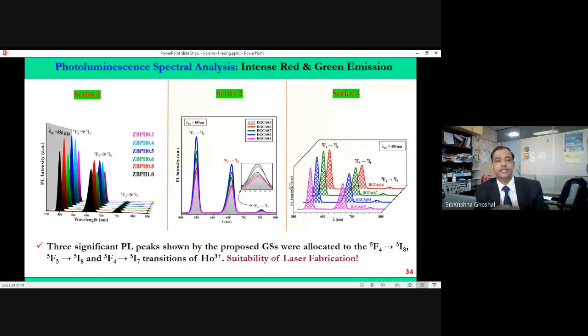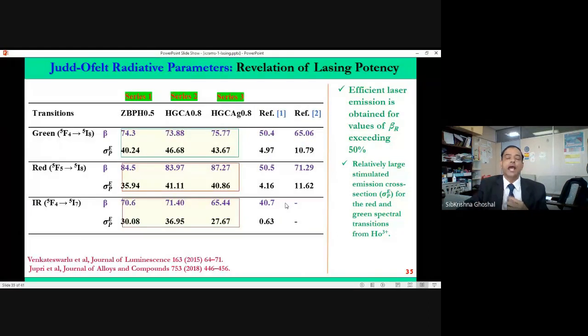Then we look for the photoluminescence, which is the emission spectroscopy. And we see intense red and green emissions. So these materials are really suitable for red and green laser fabrication. And for the first time, you can see the literature and check, for the first time we saw that we can get very high branching ratio and stimulated emission cross-section in this material. And that's why our aim is fulfilled. The stimulated emission cross-section and the branching ratio of this material is very high. And that's what we wanted to achieve. And this is the right material for fabricating the laser.